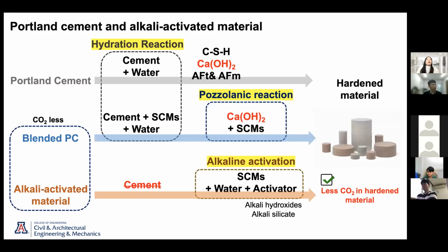I will explain the different chemical reactions in PC binder, blended PC binder, and alkali activated material binder. In Portland cement (PC) mixture, the hydration reaction occurs when cement and water mix, and it produces the main hydration products, C-S-H (calcium silicate hydrate) and calcium hydroxide.